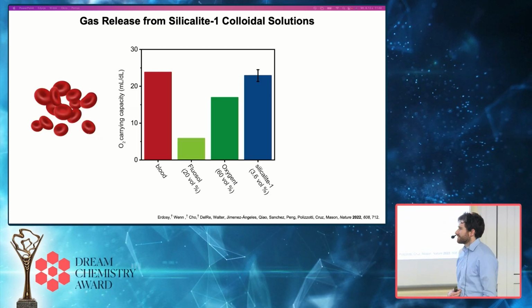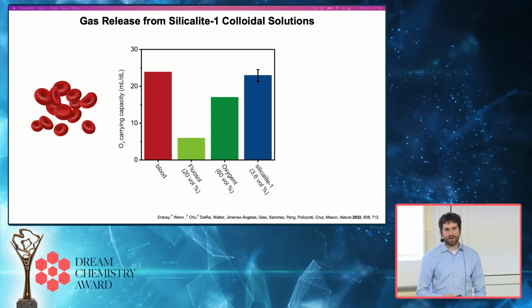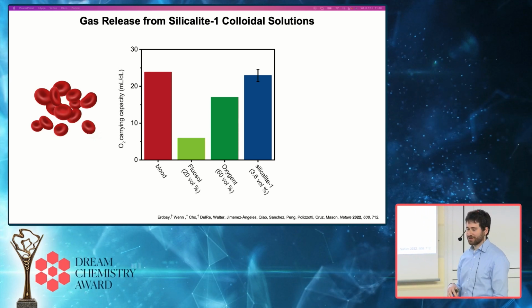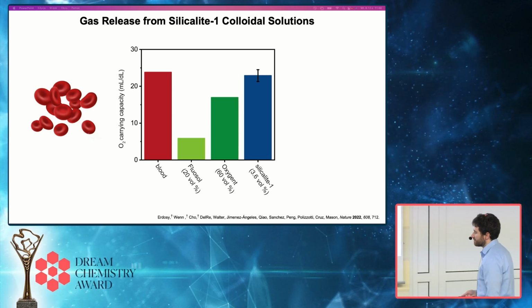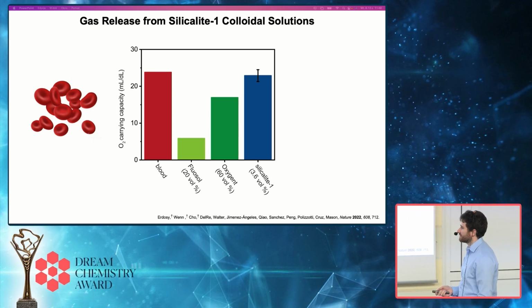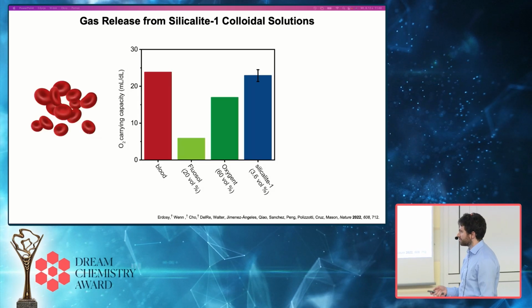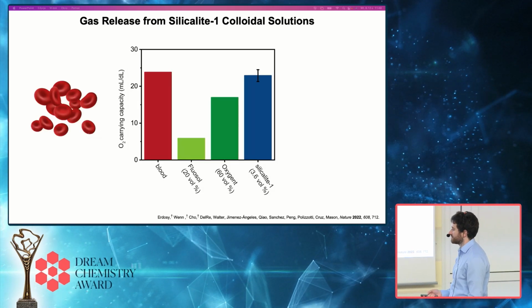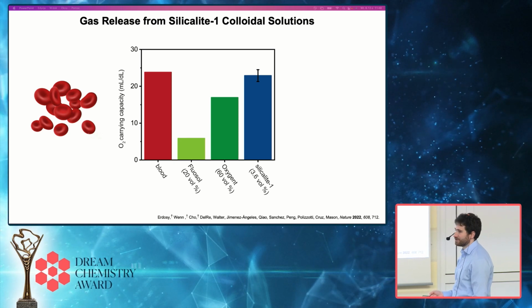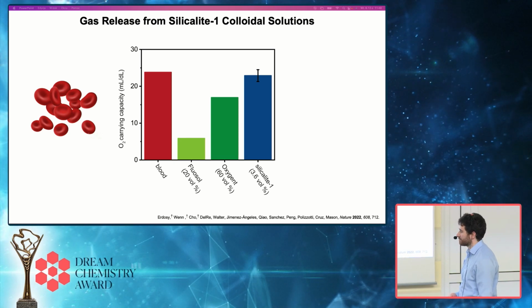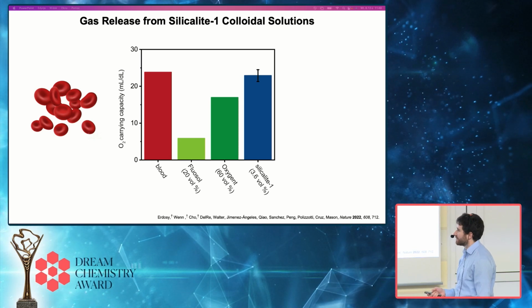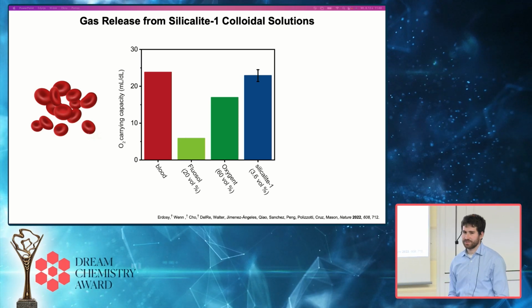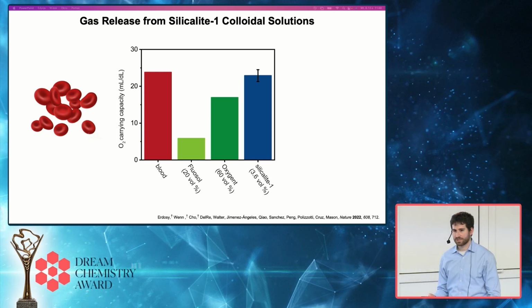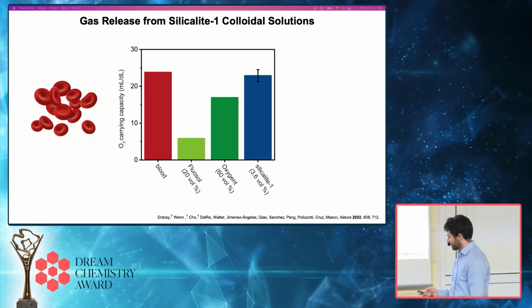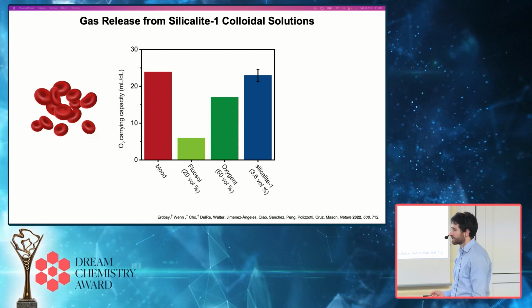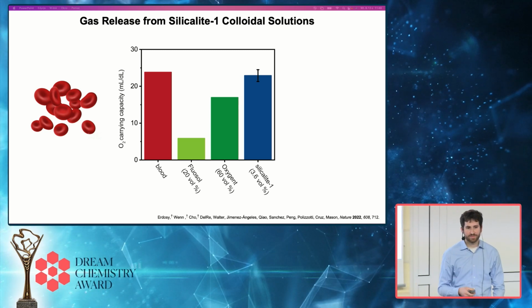So one of the reasons we got really excited about this approach was just by looking at the amount of oxygen that we were actually able to store within these solutions. And so to put this in context, just comparing here the oxygen carrying capacity of our solution, Silicalite 1, these zeolite nanoparticles, at a relatively low concentration, so this is less than 4 volume percent, we're matching the oxygen carrying capacity of blood and far exceeding what can be achieved with perfluorocarbon emulsions at much higher concentrations. And so, this solution is 96% water, but we're concentrating oxygen to the same density as what you have in blood.